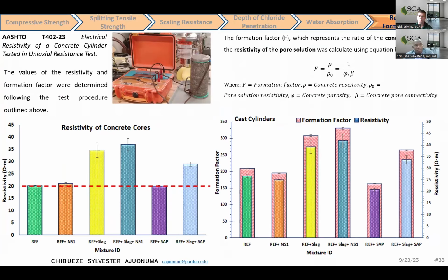And finally, we also evaluated the resistivity. We're able to assess the influence of concrete microstructure and durability, especially with respect to the ingress of water, so we measured the electrical resistivity. We found out that the concrete specimen with a greater volume of interconnected pores showed lower resistivity, but those with lower volume of interconnected pores, the concrete specimen with slag, resulted in higher resistivity, which can be beneficial to the concrete infrastructure in terms of durability performance.